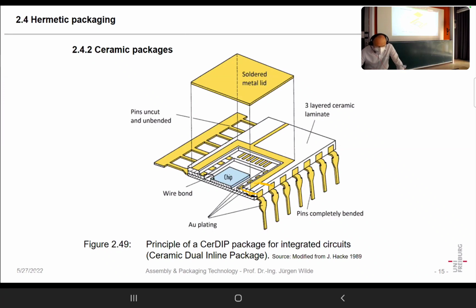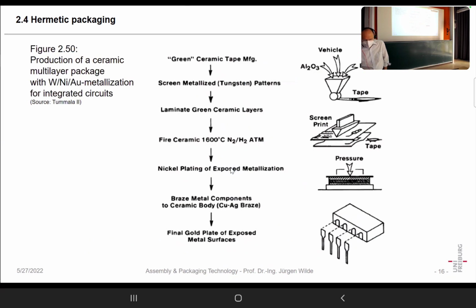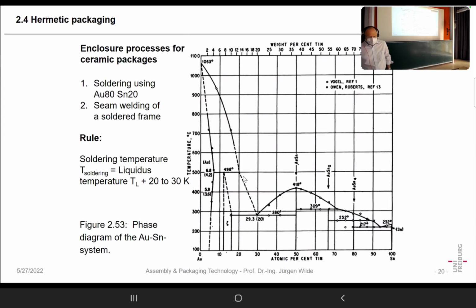And here we can see the surfaces are typically nickel, but the finish is gold. Both nickel and gold are solderable materials, and the metal we use is, in that case, gold tin with 80% of gold and 20% of tin. What is important here, we have the phase diagram, and that shows us that pure gold has a melting point of 1063 degrees centigrade. So pure gold means we have 0% of tin and 100% of gold.